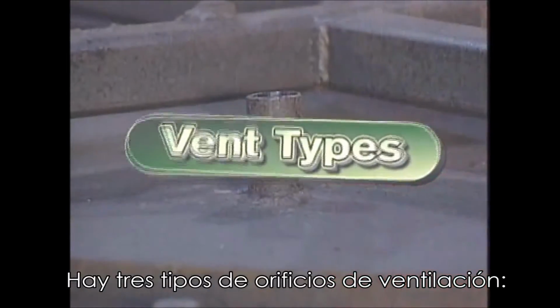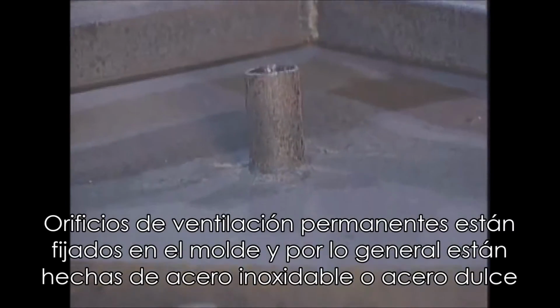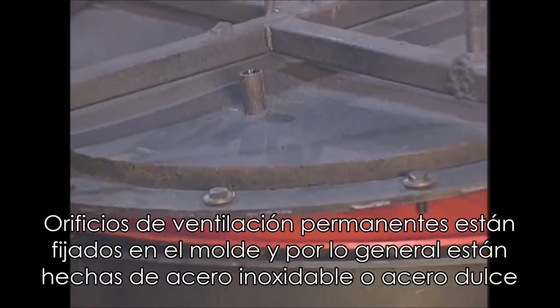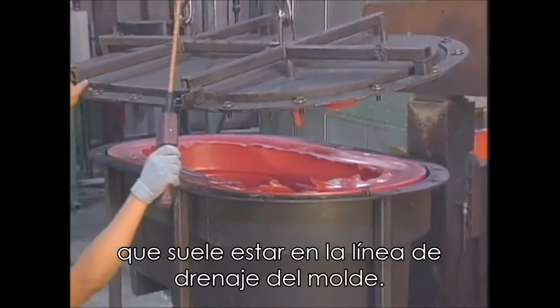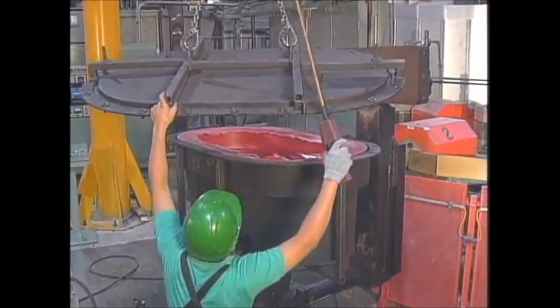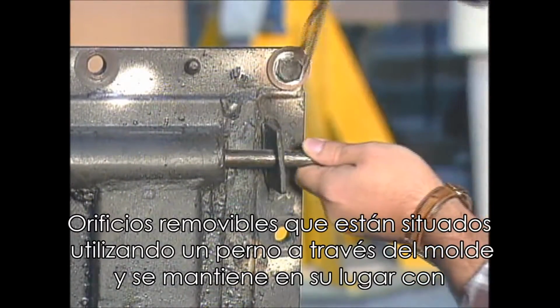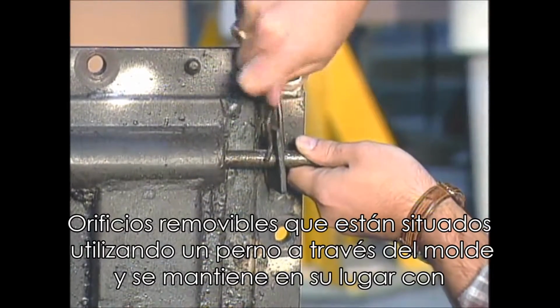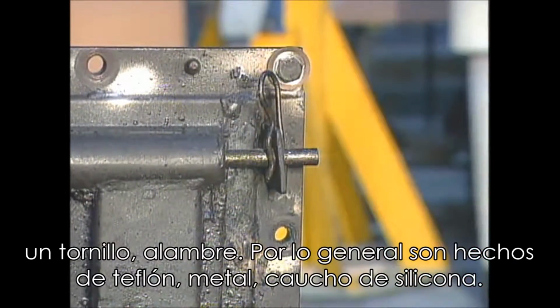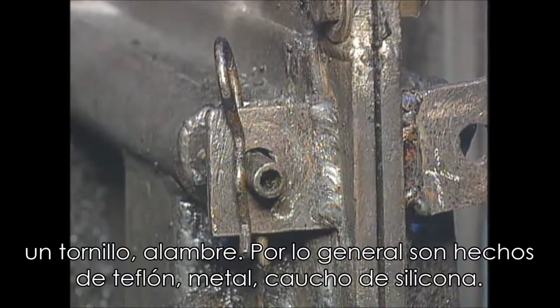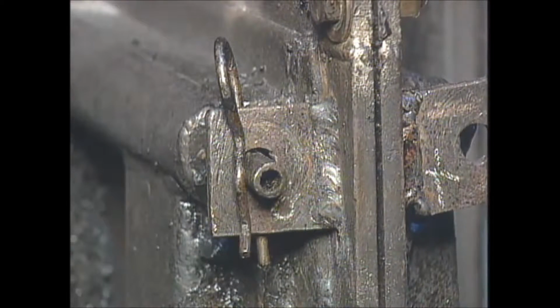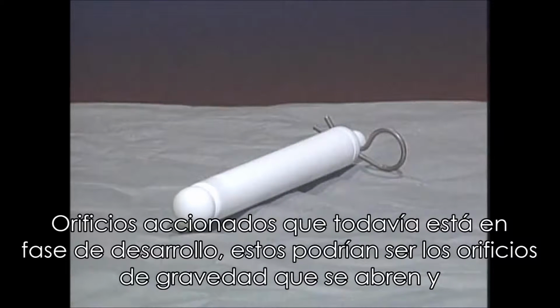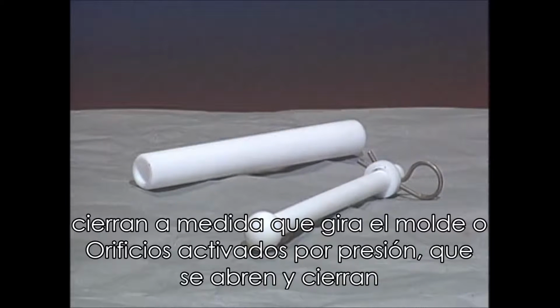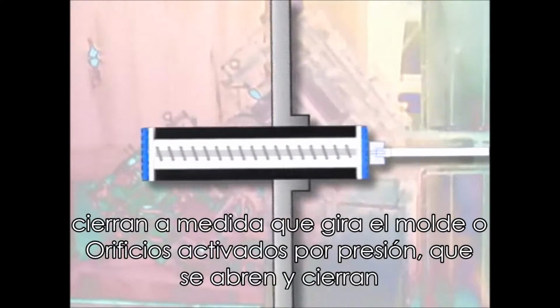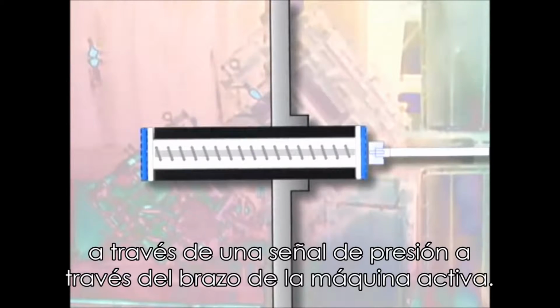There are 3 types of vents. Permanent vents are fixed in the mold and are usually made of stainless or mild steel. They will usually be in the line of draw of the mold. Removable vents are located using a boss through the mold and are held in place with a screw, wire, or clamp. They are usually made of Teflon, metal, silicone rubber, or phenolic. Actuated vents are still under development. These can be gravity vents, which open and close as the mold rotates, or pressure-activated vents, which open and close via a pressure signal through the arm of the machine.